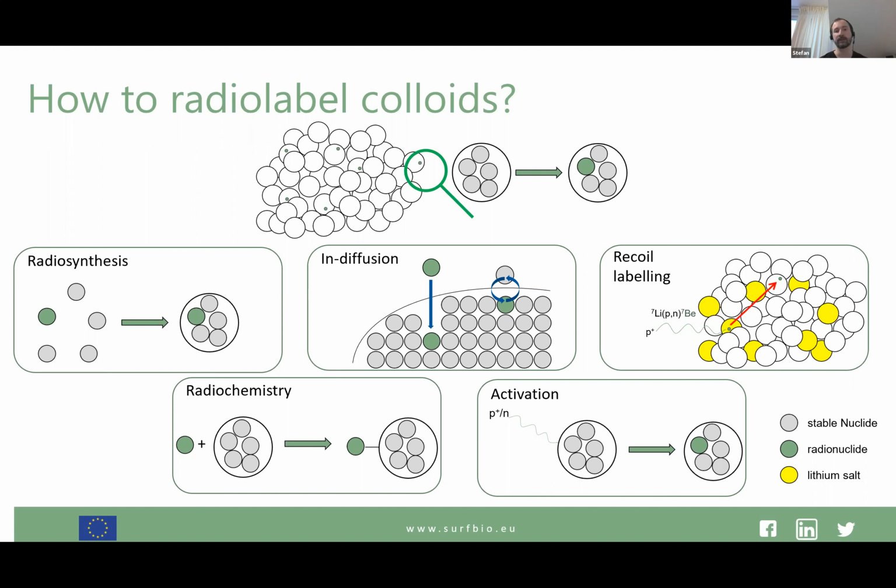And what you have to have in mind with this, again, if you do this at higher temperatures, do these temperatures change your particle or not? We have done this, for example, for cerium dioxide or titanium dioxide. These you can heat to 200 degrees easily without changing the particle properties. However, if you do the same concept with silver particles, you will just melt them down. So that is what you have in mind.